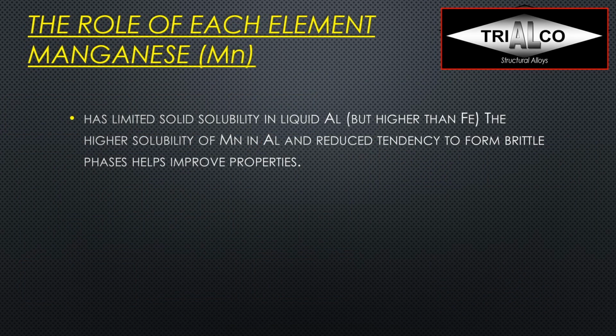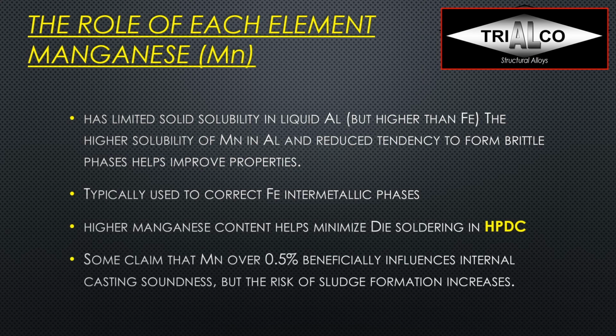So now let's have a quick look at manganese. Manganese is used, of course, in the wrought alloys, in the 3000 series alloys, but in casting alloys it's mainly used in die casting alloys or in secondary aluminum silicon alloys, and there it is usually added as half of the iron content. In die casting it is used to reduce die soldering and replace iron for higher ductility. Manganese has a limited solid solubility in liquid aluminum, but it is actually higher than iron, and the higher solubility in aluminum gives us a reduced tendency to form brittle phases and helps improve the properties. It typically is used to correct the iron intermetallic phase, and it's used to minimize die soldering, as I said. Some claim that over 0.5% beneficially influences internal casting soundness, but mind that you then run the risk of more sludge formation.